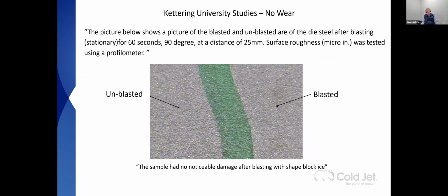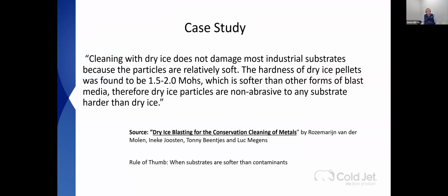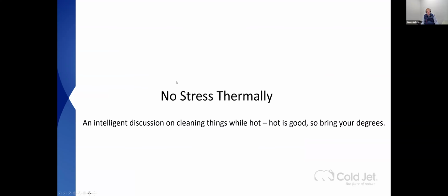Then they did some testing and they came back after blasting 60 seconds in the same place, which is not how you clean something. It's not working if you did that. But they stayed at 90 degrees for 60 seconds at 1 inch away, and they said the sample had no damage, and they tested in microinches with a profilometer. So it's gentle. That's some of the science where we say it's not damaging. There's that. And also from books in the library, cleaning with dry ice does not damage most industrial substrates because its particles are relatively soft. So there is some science out there.